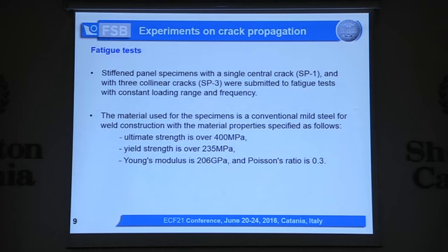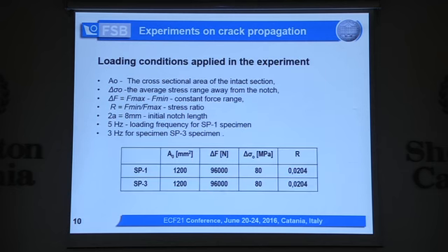And the material is mild steel for welding with yield strength 235 megapascals, and this data, as you see here, is typical material for welded ship structures. And the specimen looks like this, with its cross-sectional area, and it was loaded with delta sigma related to the intact area of 80 megapascals, and for that almost an equivalent 10-ton cyclic loading was needed. And this is the R ratio, which is basically close to zero, just a little bit above to avoid shocking in the experiment.